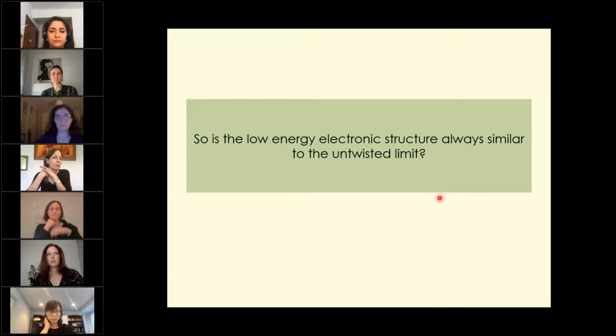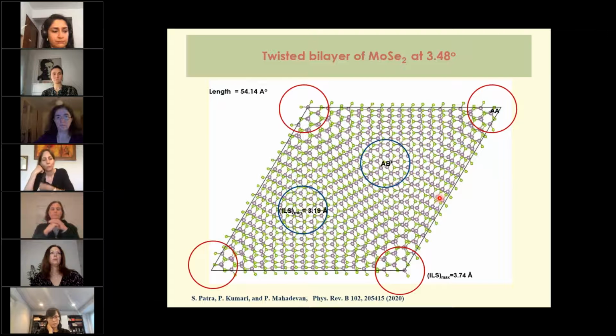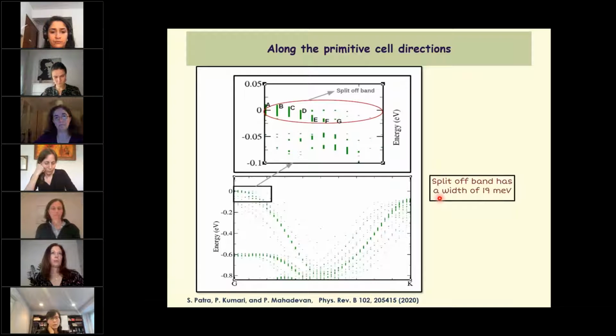So the question is, would this be true for all twist angles? And indeed, what we did was we considered the twist angles in the regime where there was interesting physics, and that is where the experiments have been done, around 3 degrees and 4 degrees and so on. So I'm just showing you one of the results, where essentially what you see is that we do have a band which emerges out, which is split off from the rest of those dispersing bands, indicating, as earlier, that